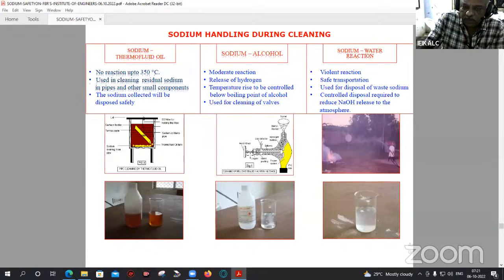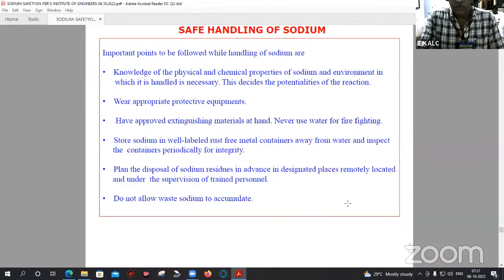The second one is alcohol. This is very much required. Suppose I am cutting a line, I have to clean the pipeline before introducing another one. Suppose a valve fails, removing the valve and putting in a new valve. The pipeline has to be cleaned with alcohol and thoroughly cleared. Sodium has to be removed. Particles of sodium have to be removed. Only then can welding be taken up. So alcohol is used for cleaning purposes. And finally, sodium waste disposal can be done by using water, because sodium reacts with water and forms sodium hydroxide and hydrogen. But there are also some disposal yards where the sodium can be disposed of.